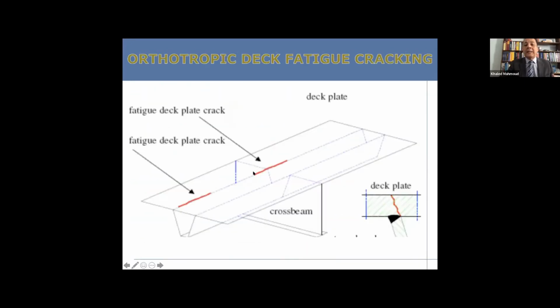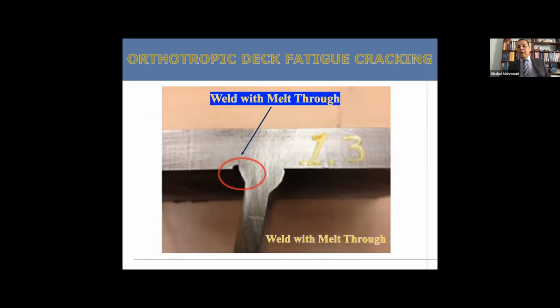So basically, here's the kind of crack that develops in the deck plate, and you can see here the cross section. What we do is testing. Almost all the jobs that we have been involved with on the orthotropic deck for a suspension bridge, we have been doing testing, and you do the testing to qualify the welding technology that is automated and find the heat input and many other parameters. The technology is wonderful, but what we need to do is to qualify this technology so that it does not cause what's known as melt through.